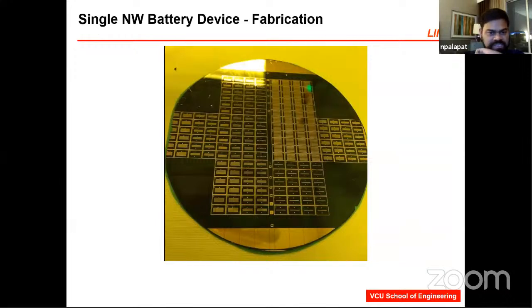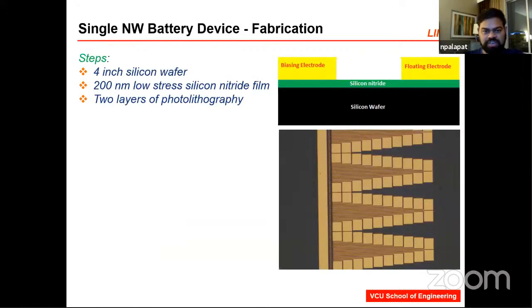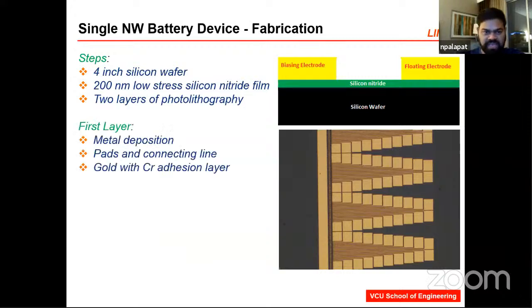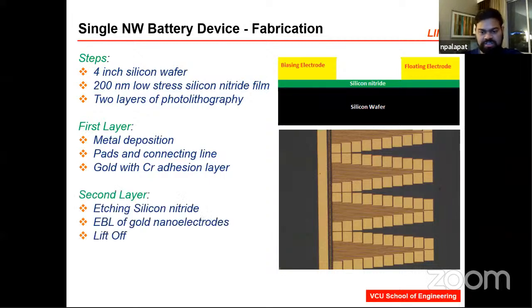So this is how the 4-inch silicon wafer would look with different designs as fabricated. Giving more information, it involves a two-step photolithography process. The first step involves developing these bigger pads, and then the second step involves electron beam lithography, then liftoff, focusing particularly on the gap locations, the electrode locations.